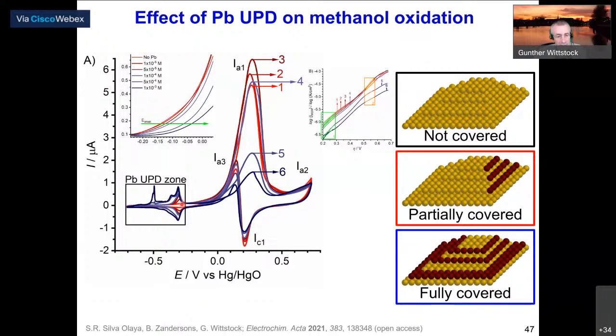And that was a bit of a surprise to us: the high energy surface sites on that material, where we have defects mainly in the 100 layer, are not really important for the electrocatalysis. These are more the terraces of the 111. If they are occupied, the current drops enormously, and therefore they make the major contribution. Here is just a pictorial representation, which is not the correct surface structure, but the idea of the experiment: we selectively decorate certain surface sites by changing the amount of UPD lead and then explore what the remaining sites do for the methanol oxidation.